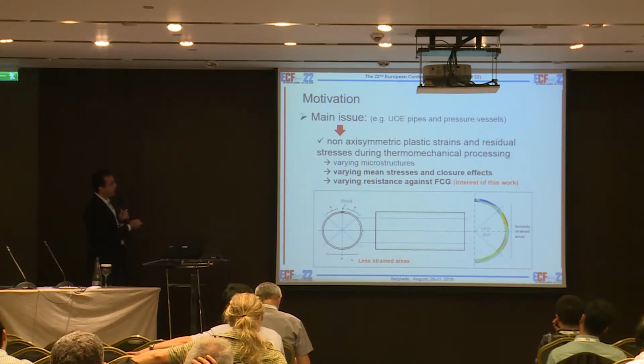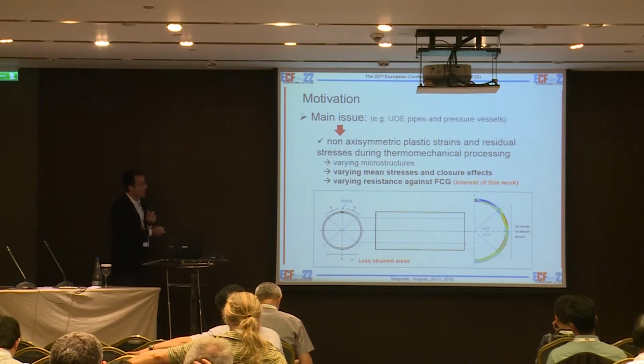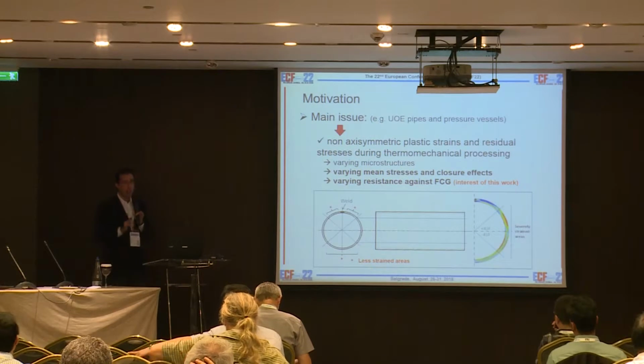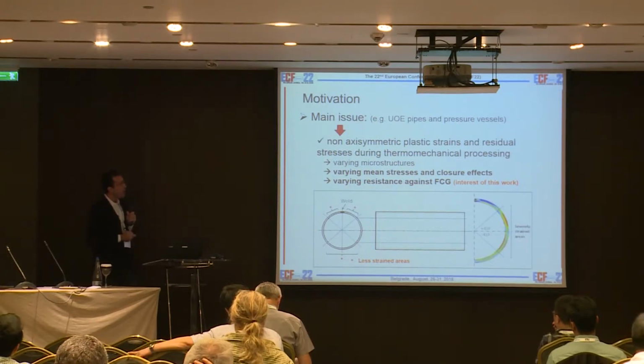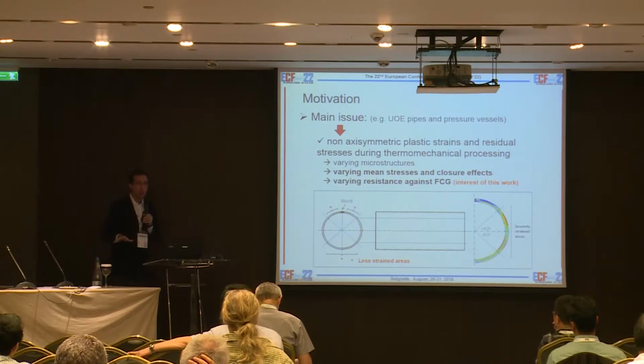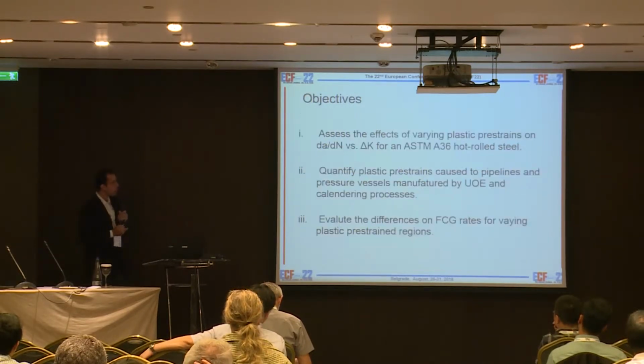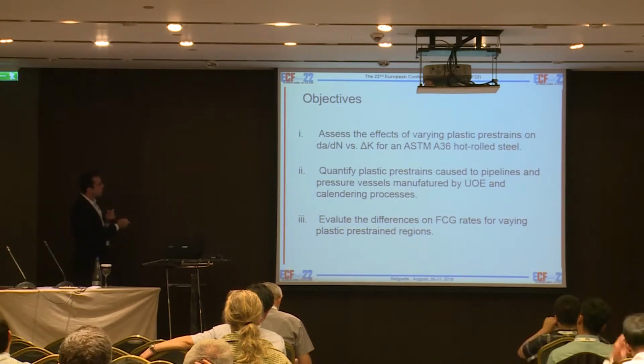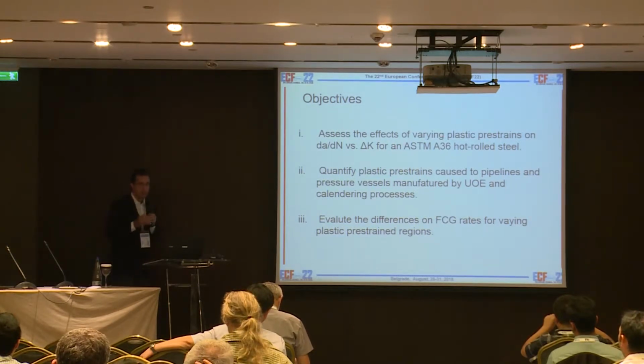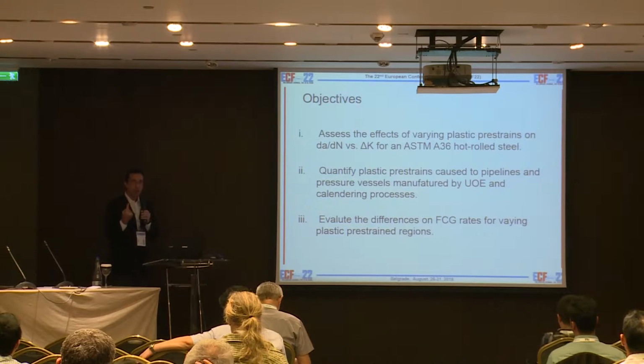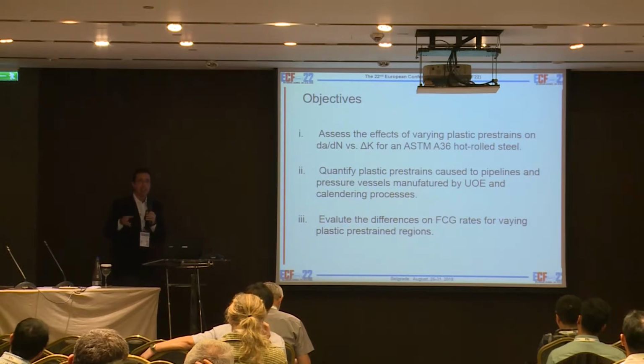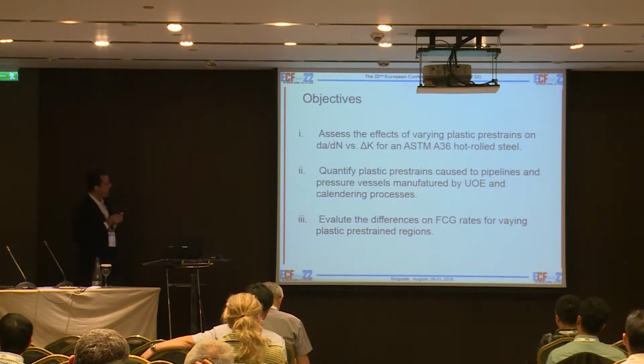Microstructures are thus varying, and we have varying mean stresses and closure effects, and thus the behavior in terms of fatigue crack growth. Here we are studying the fatigue crack growth behavior just to illustrate. The dimensions are not of the real components, but they are illustrative dimensions to show you what happened. So the objectives include to assess the effects on an ASTM A36 hot rolled steel. This was the steel used in one of the applications. The others employed API 5L steels, grades X65, X70, and X80.